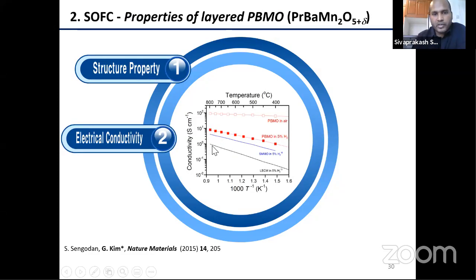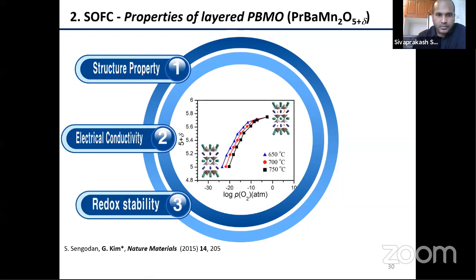These are other alternative anode materials: lanthanum strontium chromium manganese oxide, which shows about 1 Siemens per centimeter, and another double perovskite material, SMMO, strontium magnesium molybdenum oxide, which shows about 5 Siemens per centimeter in 5% hydrogen at 800 degrees Celsius. But my material shows about 10 Siemens per centimeter in 5% hydrogen, and it is also redox stable.